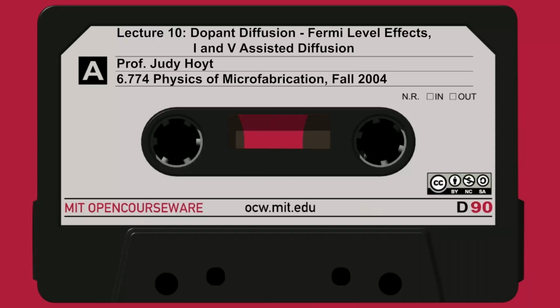All right, fine. Well, if they just switch back, they haven't moved anywhere. If they're just switching back and forth, that doesn't do you any good. But imagine I move the dopant to this point, and the vacancy moves up to there. Now, all of a sudden, this vacancy is sitting here. It can move independently for a second of the dopant and exchange with this neighboring silicon atom. So now I have a vacancy here and a silicon atom here, and the vacancy can move over here. So all of a sudden now the vacancy is sitting over here, again next to that dopant atom. Now I can exchange with it.